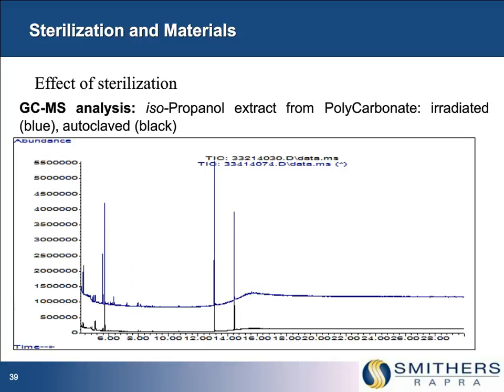Another example. So this time we've taken a polycarbonate. We're doing the GCMS analysis, so rather than the very volatile species, there are semi-volatile. And the difference in the chemical species between the irradiated or autoclaved are negligible. There's a small amount more on the irradiated sample, but those are really down in trace levels. And again, with the sterilization and the analysis, we've actually had to use a different analytical technique. So these are the areas that I haven't had a chance to go through in the webinar, namely what are the approaches to the analysis of extractables and leachables?